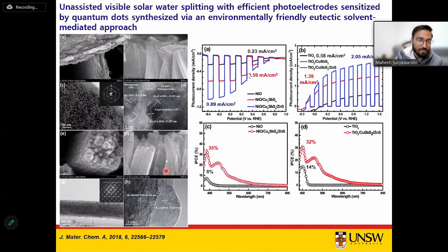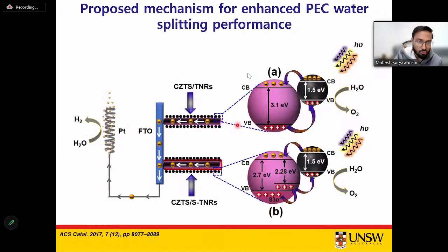okay, this system. In one of the works, if you take a clear look at this schematic, you will understand what we have done: we have prepared one electrode which acts as an N-type photoelectrode, or N-type photoanode, where there will be only the oxygen evolution reaction, right? But if you see on the right side, where the hydrogen will be produced, it's still platinum, right? That means if we develop the system for large-scale commercialization, we again need to consider the platinum cost, which will again cast doubt on the feasibility of our system.